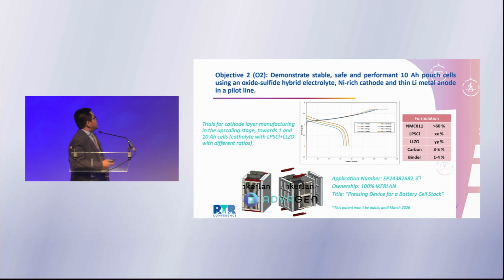The next objective is trials for cathode layer manufacturing in the upscaling stage. Previously we tried it in the coin cell, and in the coin cell we got quite high capacity. But for cathode layer manufacturing at the next capacity, which is more than a monolayer, at 1 ampere hour and 10 ampere hour, we need to optimize again. In the coin cell we can use a pellet, or a simple way to make the solid state electrolyte, but for pouch cells of 1 ampere hour to 10 ampere hour, we cannot use the same method.